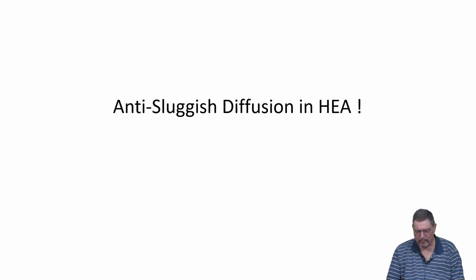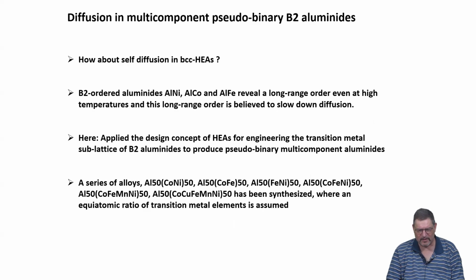Now, there is one instance where we really have anti-sluggish diffusion in high entropy systems. And this is when we look at diffusion in the multi-component pseudo-binary B2 aluminides. So we look at these aluminum nickel, aluminum cobalt, aluminum iron. They reveal long-range order even at high temperatures, so they are very stable as ordered alloys. And as you probably know, strong ordering tendency in an alloy makes diffusion decelerated. Why is this?